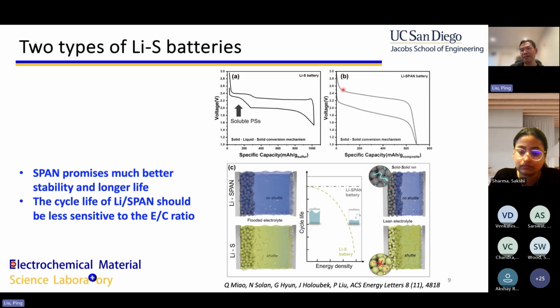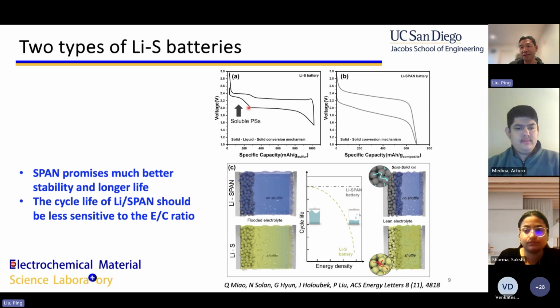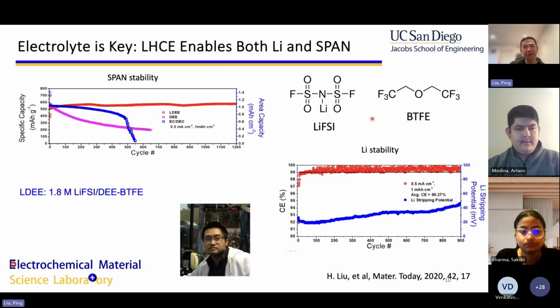What people have found with elemental sulfur is that, because the polysulfide needs to dissolve in order to move the reaction forward, the battery behavior is heavily dependent on how much electrolyte you add in. But if you add a lot of electrolyte, it doesn't really store any energy, and that would kill the cell level energy density. So keep in mind there are two different kinds of lithium sulfur batteries, and we primarily work on this type. The key is to find a new electrolyte that will allow this material to be stable.